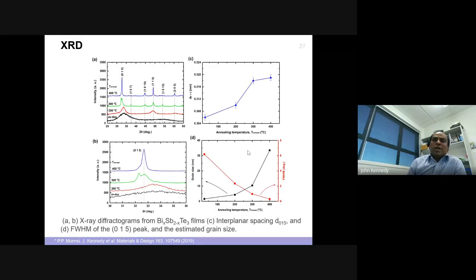So what happened in the crystal structure? We managed to form an amorphous film as deposited, which is good. Then, depending on the annealing condition, we can crystallize them to polycrystalline or crystalline. This suggests that you are playing with the grain size. And when you're tuning the grain size, you start playing with the interplanar spacings as well. So you can estimate something must happen to the crystal structure. We looked quickly at what happens there.